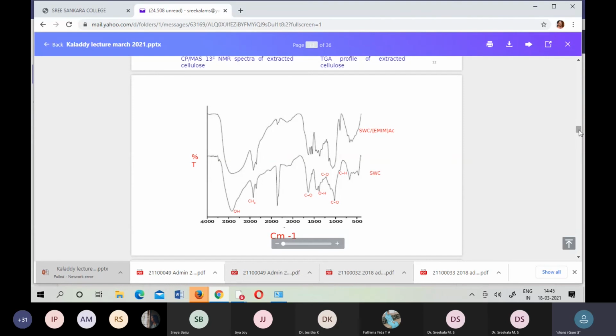The final conclusion is we are able to get close to 16% of the seaweed cellulose. We can dissolve it in ethyl methyl imidazolium acetate at 90 degrees Celsius. The total dissolving time is just 10 minutes. So what we did is, when we prepare the film and soak it in water, the ionic liquid, which is water soluble, we were able to recover from the water bath and reuse close to 4 or 5 times. And whatever final film we are getting, the quality is the same.